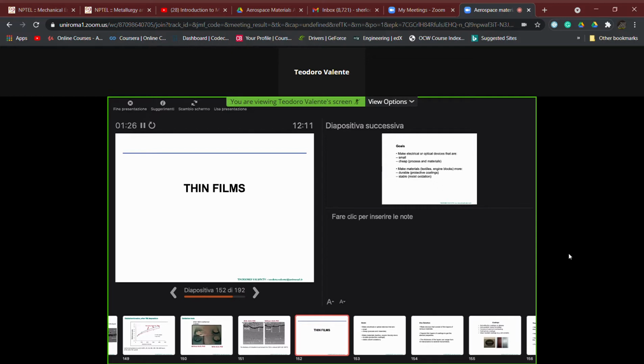even though they exist, but they are special cases, like those, for example, for fabrication of ceramic fibers used in composite materials. Even though they exist, let me say again, as exception, thickness of coatings which can reach 100 and 150 microns. But on average, for the techniques which are not used for fiber fabrications, but for coating fabrications to our purposes, we have the upper limit, which is around some micrometers. Some means 3, 4, 5, 6, sometimes 10, but no more.